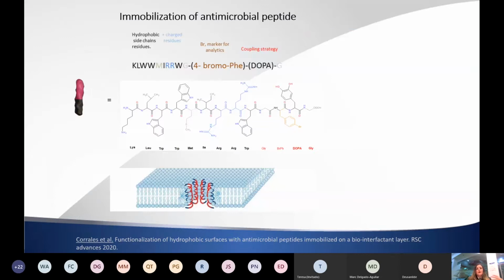So we went further, and we immobilized antimicrobial peptides on the surface, because if we have a medical device made of polystyrene, for example, normally these materials are not antimicrobial. So we wanted to make these materials antimicrobial in an easy way, in a way that a medium company can use this procedure without fancy equipment. We first made a layer with the laccase, where the enzyme is still active. It doesn't mean that when the enzyme absorbs on the surface of the polystyrene, it's not active afterwards. It's active.